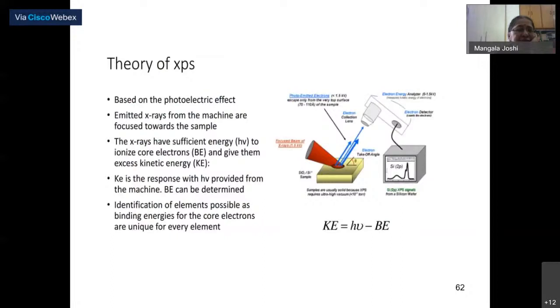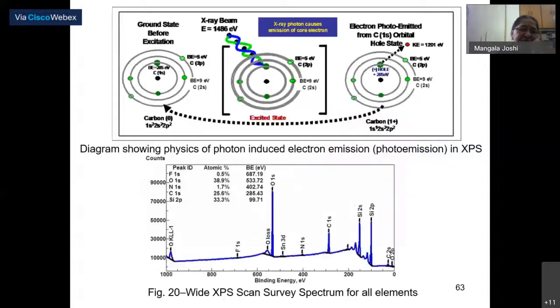The theory of XPS is based again on the photoelectric effect. X-rays emitted from the machine are focused towards the sample, and the X-rays have sufficient energy to ionize the core electrons, overcoming the binding energy, and give them excess kinetic energy. So h nu is the energy which you are giving, and binding energy is the energy required to ionize the core electrons. If you have given more energy, then those electrons will have a kinetic energy. KE is the response to the h nu provided by the machine, and the binding energy can be determined. So identification of elements is possible, as binding energies for core electrons are unique for every element. This is the basic principle of XPS.